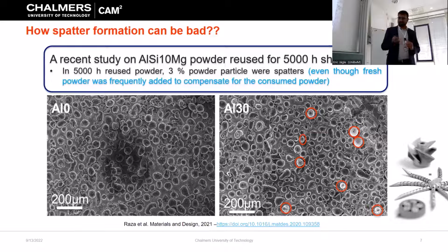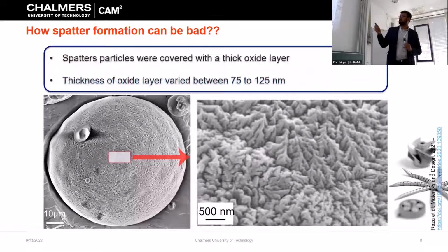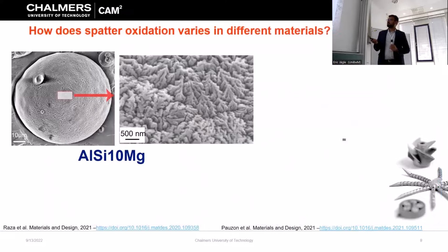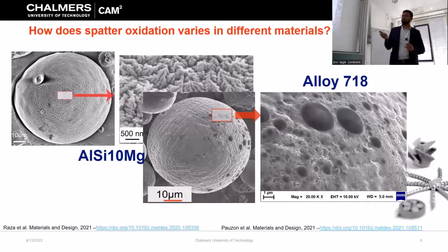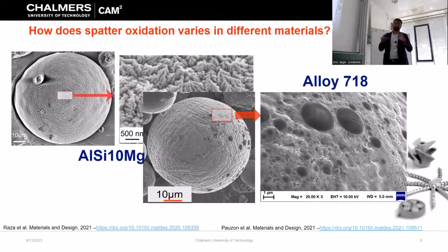And when we looked at the surface of these spatters, they were covered with a very thick oxide, with an oxide layer thickness of 75 to 125 nanometers. Then we wondered, okay, aluminum oxidizes this way, but do all alloys oxidize in similar fashion? We did this with alloy 718 and checked the spatters. Well, it is quite different. In that alloy, we saw some particulate formation and some oxide patches.